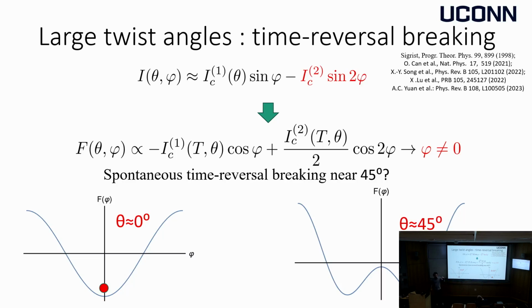Let's remember that the time reversal operation in quantum mechanics is essentially equivalent to complex conjugation. Therefore, if you are creating a complex phase that you cannot get rid of, and you have two different minima with non-zero complex phase, that means that each of them breaks time reversal symmetry. So what is expected is that at 45 degrees, not only you will have some critical current remaining, some superconductivity across the interface remaining, you also expect the interface to be time reversal breaking.